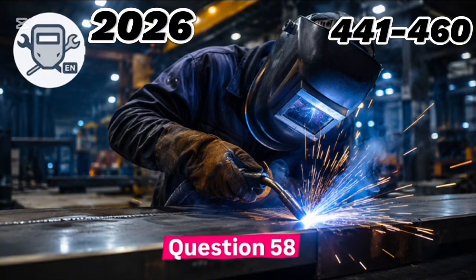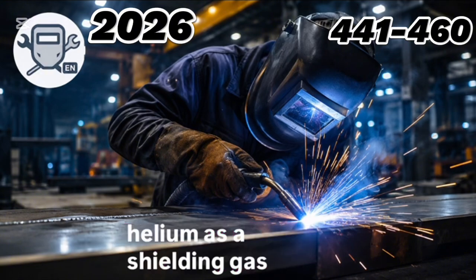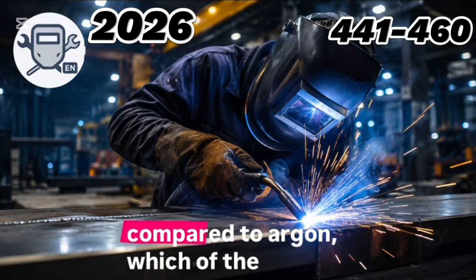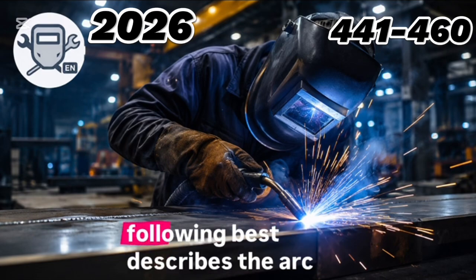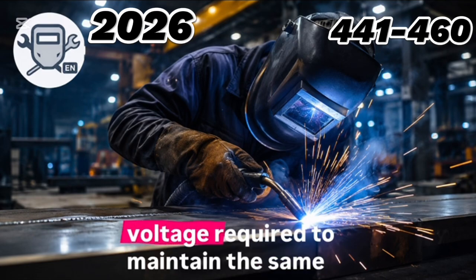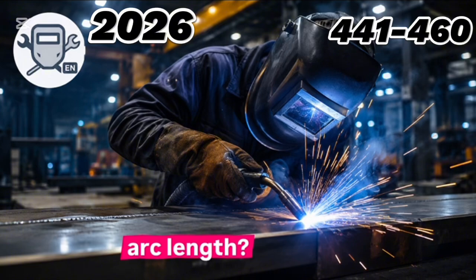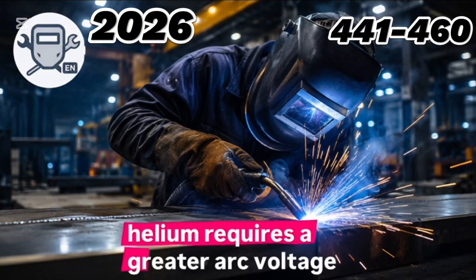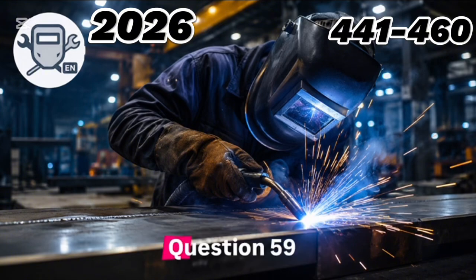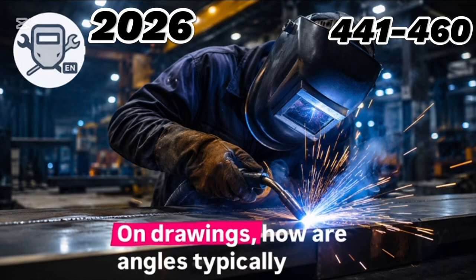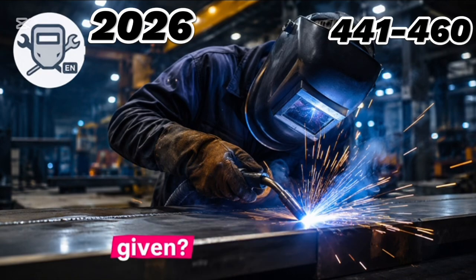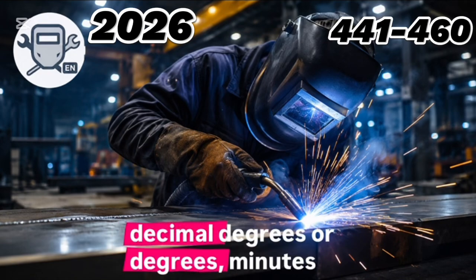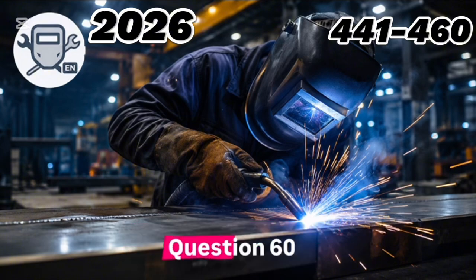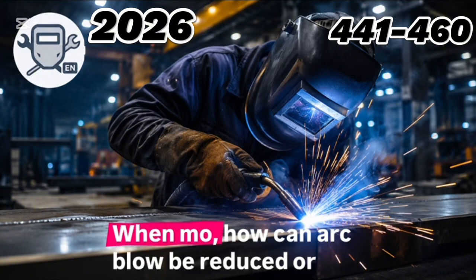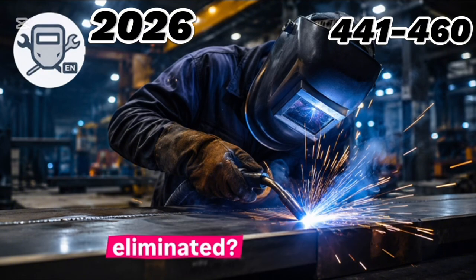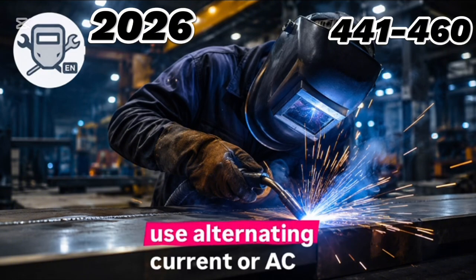Question 58. When gas tungsten arc welding with helium as a shielding gas compared to argon, which of the following best describes the arc voltage required to maintain the same arc length? Answer: helium requires a greater arc voltage. Question 59. On drawings, how are angles typically given? Answer: decimal degrees or degrees minutes. Question 60. When welding, how can arc blow be reduced or eliminated? Answer: use alternating current or AC.